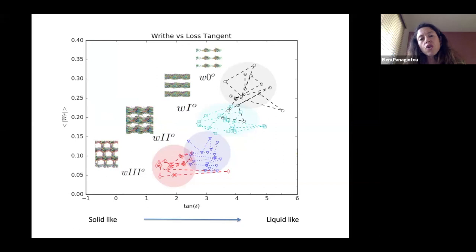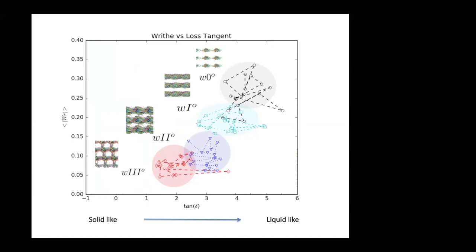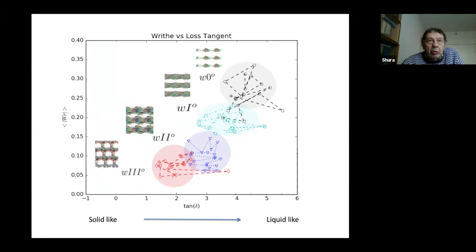So a larger writhe, in a situation where there is no entanglement with other chains, would increase accordingly, following some power law of the length, the molecular weight of the chains. Right, and the viscosity and the fluid of the whole thing. I see. Mm-hmm. Yeah. Eleni, but as far as I understand, you don't have hydrodynamic interactions here in your simulation. Therefore, your friction coefficient for a polymer is just proportional to the number of monomers, and it is not affected by its conformation.